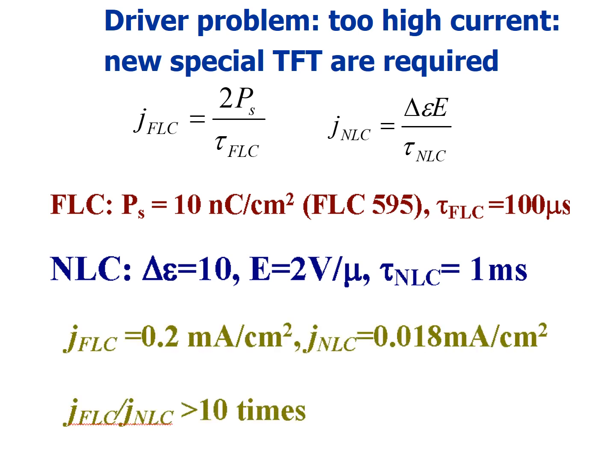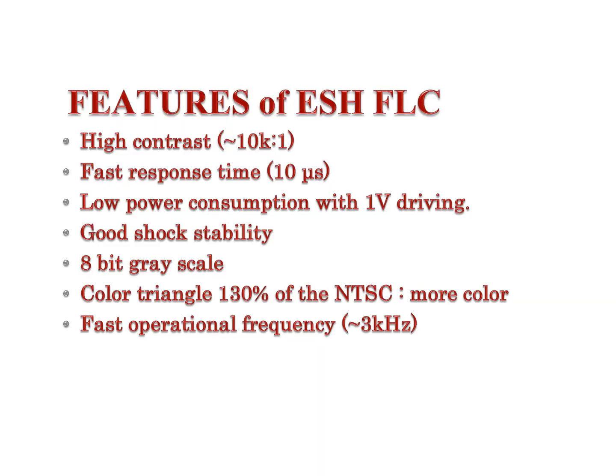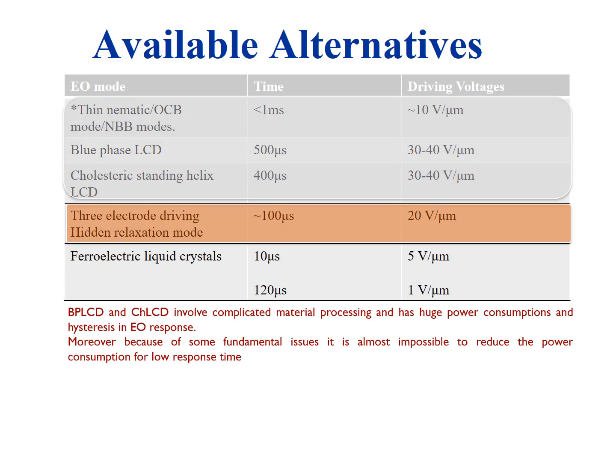We use IGZO or low temperature polysilicon transistors. So finally, we get excellent field sequential color displays with high contrast ratio, fast response time, mechanically stable, excellent color triangle. So if you compare our photoaligned ferroelectric liquid crystal mode with other electro-optical modes, we can tell you that ferroelectric liquid crystal can get 120 microsecond response time for plus minus 1 volt per micron. It is also possible for other modes, but they use much higher voltage.